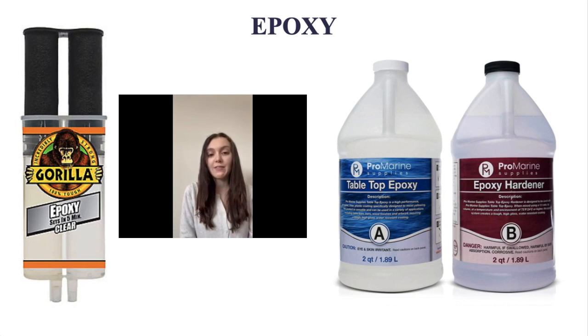The issue is that the curing reaction is very exothermic, and the heat that builds up within the epoxy is transferred to the glass fibers, causing them to break due to an accumulation of thermal stress.